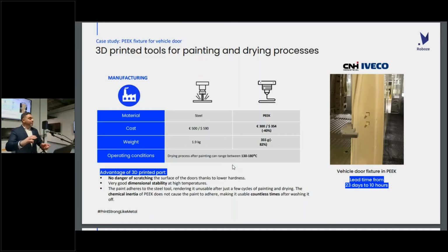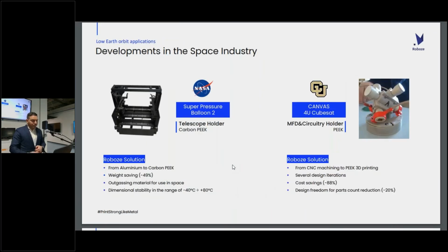So we printed the same jig in PEEK. PEEK has very good self-lubricating properties, so nothing pretty much sticks to PEEK. And they could wash it in autoclave, whatever they needed, without losing performance. So they went from changing 10 jigs a week to using one that lasted 4 months.